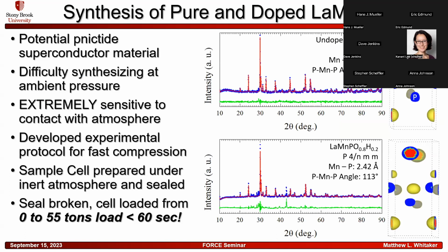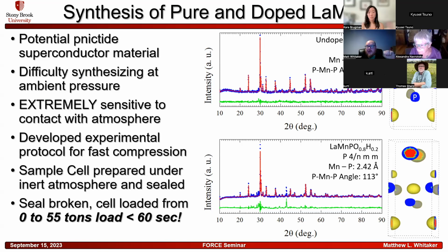We took the sample cell that was prepared under an inert atmosphere and sealed in a glove box. We brought it over to the Beamline, and we took it to the press, and we shattered the glass ampule that it was in, put it in the press, put the anvils around it, and then we loaded the cell from 0 all the way up to 55 tons in less than 60 seconds, which is extremely fast for a DIA, considering that the maximum load that we normally put on the DIA is 60 to 65 tons. This was extremely fast. We were able to successfully manage the environmental contamination of the material and prevent it completely.